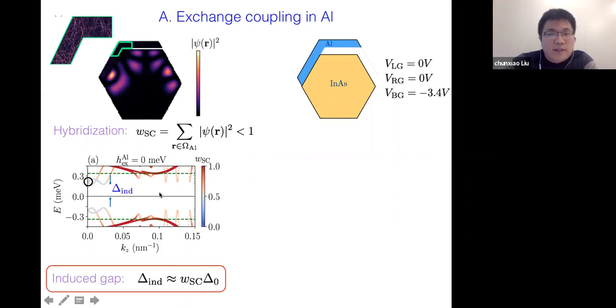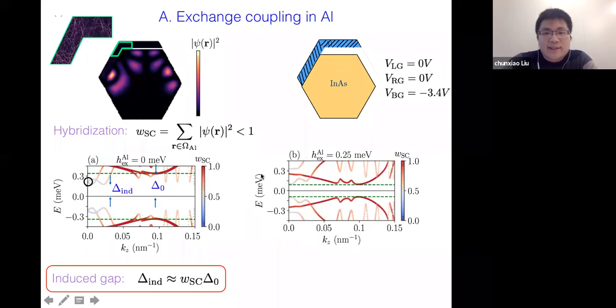On the other hand, we see this red band structure. It's the superconducting state, with all of its wave function inside the superconductor. So the gap is just the bare value delta naught, right? And these states are other subband modes for the hybrid state. And now we switch on the exchange coupling inside aluminum, and the band structure becomes this.